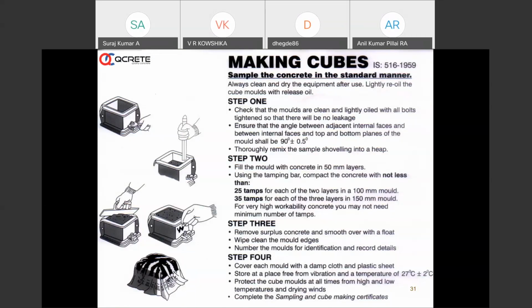There is an elaborate method described in IS 1199, and then we have the standard procedure explained in IS 516 1959 on the making of cubes. We can have 35 strokes, 3 layers, and many times we neglect this. Untrained personnel will make cubes in different ways. If the compaction is not good, if the casting is improper, and if the cubes which are cast are not protected immediately before we transfer them to a curing facility, then it will be a problem.